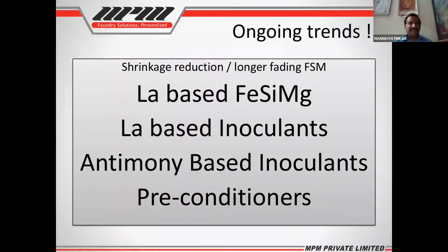Okay, so this is for the elemental effect. So what are the ongoing trends? For shrinkage reduction, longer fading FeSiMg. Now the ongoing trends are lanthanum based FeSiMg, lanthanum based inoculants, and antimony based inoculant. Some foundries are using preconditioner, but it's again a question whether they need a preconditioner or not. Because in earlier days when people were not using pig iron, definitely people were looking for the preconditioner because of some added advantage, but it has to be evaluated and re-evaluated whether we really need a preconditioner or not.